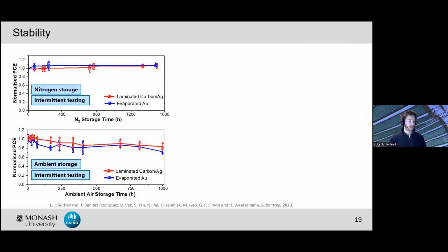And what we're able to see is that under storage, both electrode types exhibited similar efficiency. So this is after 1,000 hours and 1,600 hours storage in nitrogen and ambient. And yeah, there's not a huge difference. I mean, we can see the carbon electrode maybe slightly outperforms the evaporated gold in ambient storage, but overall, there's not a huge difference.